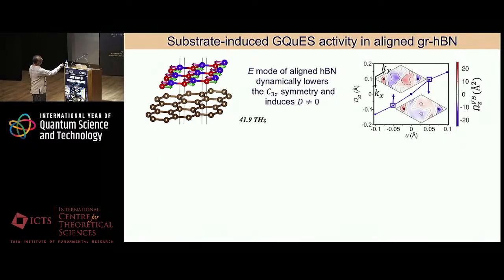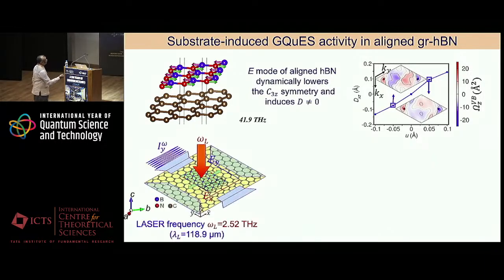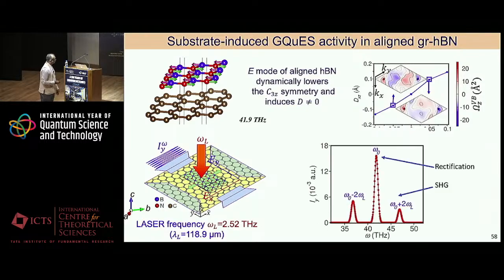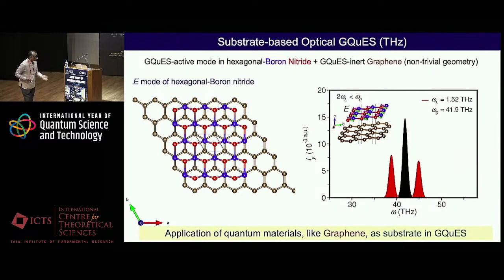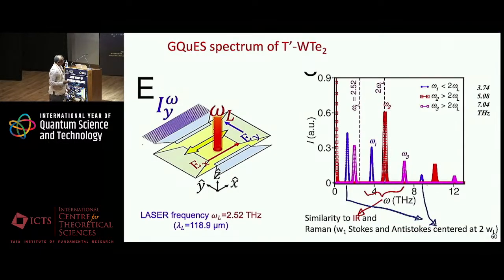But if you deposit it on graphene, its vibration can induce oscillations in the Berry curvature dipole of graphene, and that can be measured. We have calculated it from first principles, and we predict this is the spectrum one should see for hBN deposited on graphene. So this really expands the applications of quantum geometry-based spectroscopy to a wide variety of materials. In fact, it's an application of a quantum material like graphene in measuring vibrations of other systems which may be rather sensitive. Okay, I will skip all of this now.